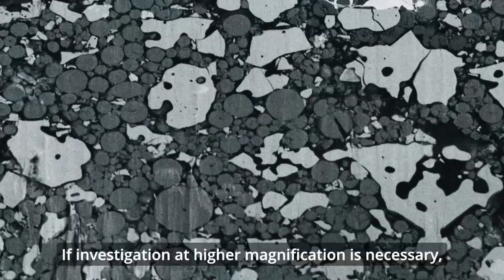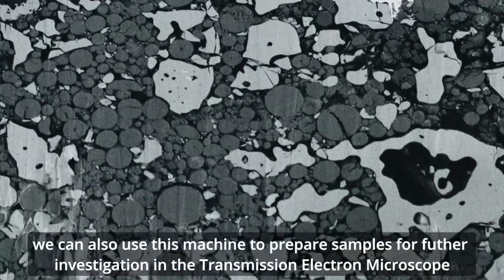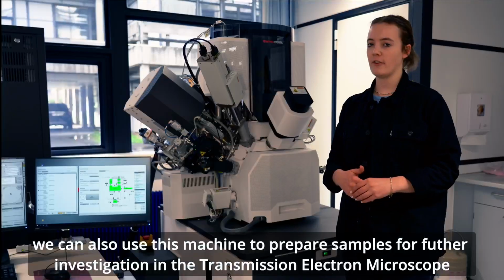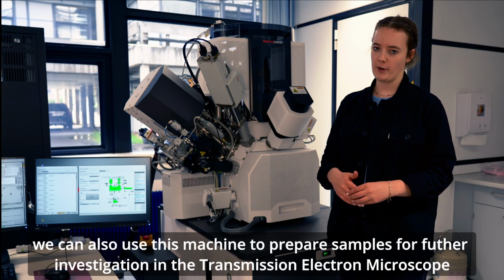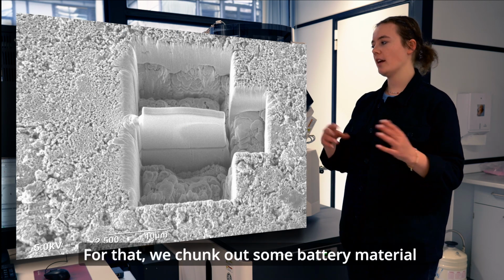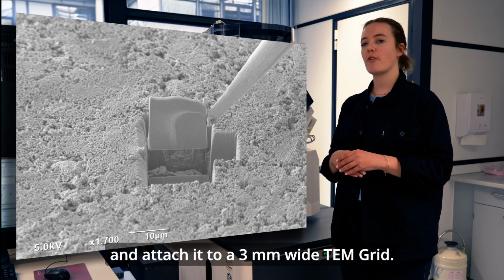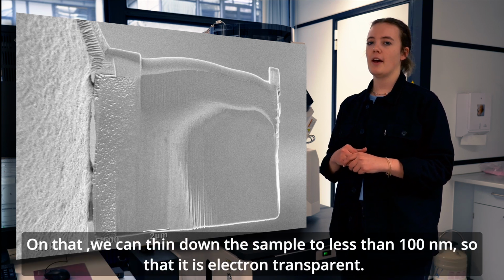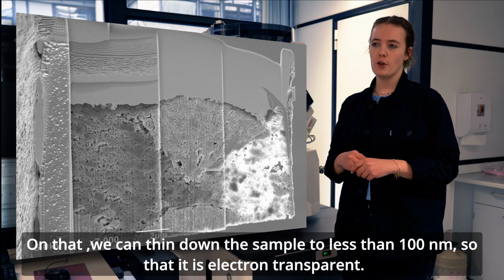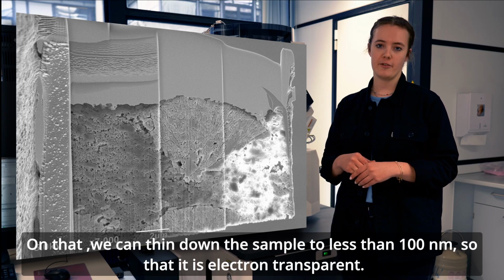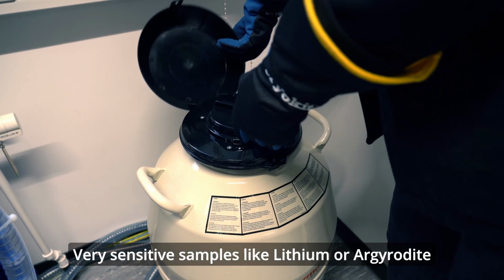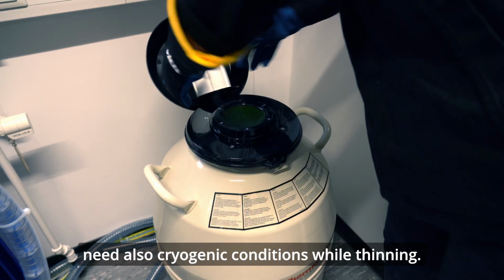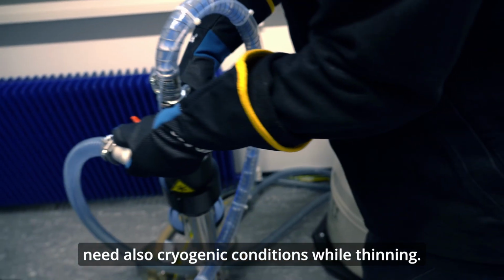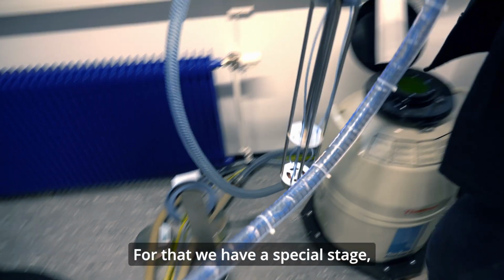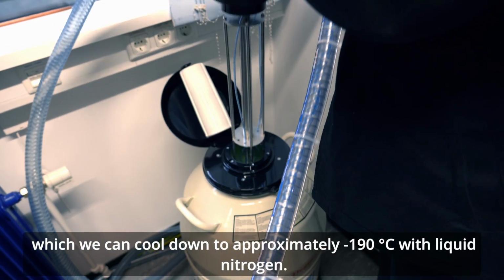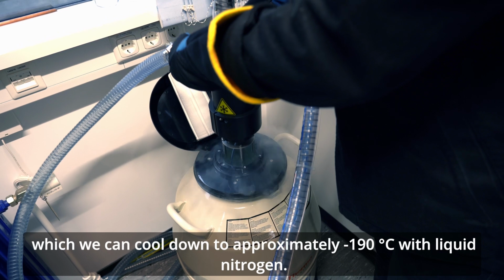If investigation at higher magnification is necessary, we can also use this machine to prepare samples for further investigation in the transmission electron microscope. For that, we lift out some battery material and attach it to a 3 mm wide TEM grid. On that, we can thin down the sample to less than 100 nanometers so that it is electron transparent. Very sensitive samples like lithium or similar materials also need cryogenic conditions while thinning. For that, we have a special stage which we can cool down to approximately -190 degrees C with liquid nitrogen.